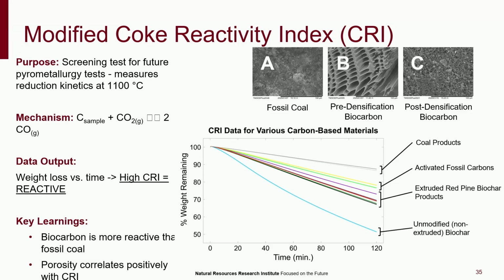And so unmodified, just biochar as is, was the most reactive, and the coal products at the top were the least reactive. We threw in some activated fossil carbons just to get a representation, and then extruded or densified material, you can see how much we improved or decreased the reactivity. And so what we learned is that biocarbon is more reactive than fossil coal, and porosity does correlate with the CRI. So you can see here, this is the SEM image of the fossil coal. This is the pre-densified biocarbon that still has that structure, all the pores, and then our densified material on the far right. And you can see how it's a lot more comparable to the fossil coal.